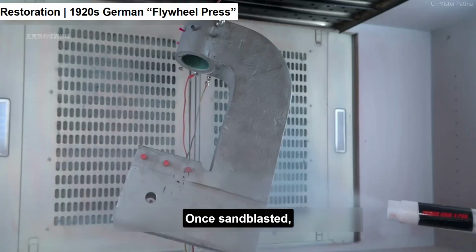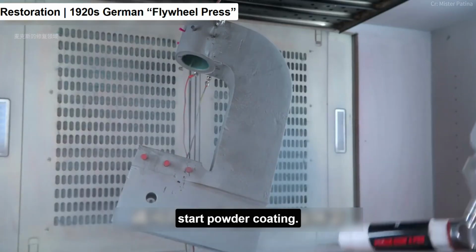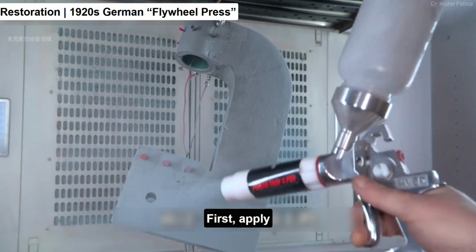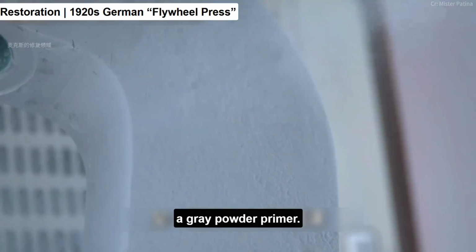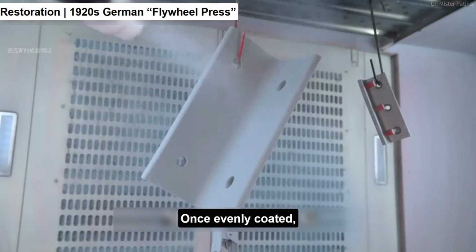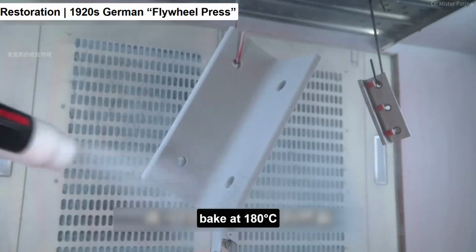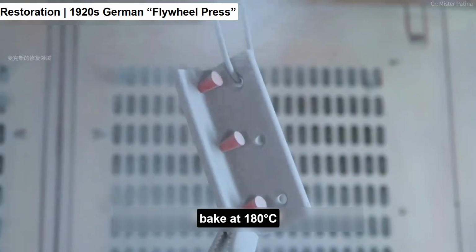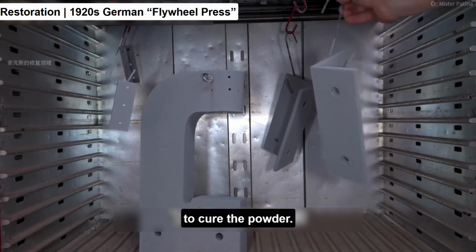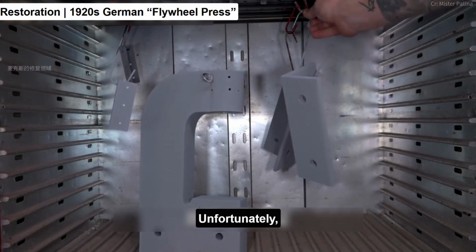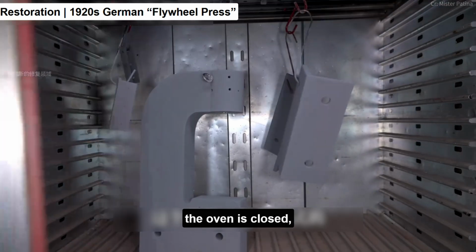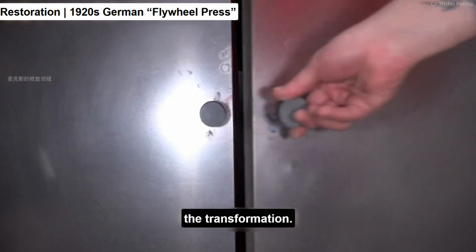Once sandblasted, start powder coating. First, apply a gray powder primer. Once evenly coated, bake at 180 degrees Celsius for 10 minutes to cure the powder. Unfortunately, the oven is closed, so we can't see the transformation.